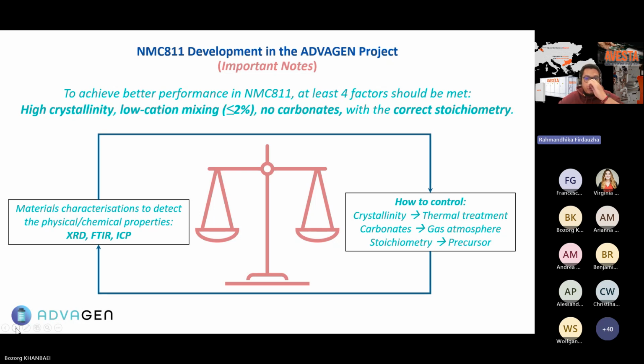And how to control that? Crystallinity, we have to control with the thermal treatment. Carbonates, we control by the gas atmosphere, and stoichiometry, we have to control by the precursor. And then once we control all of this, we have to characterize to detect the physical chemical properties, at least with XRD, FTIR, and ICP, to check the result of our product. And then again, if in the material characterization we don't have sufficient performance, then we come back to how to control that.